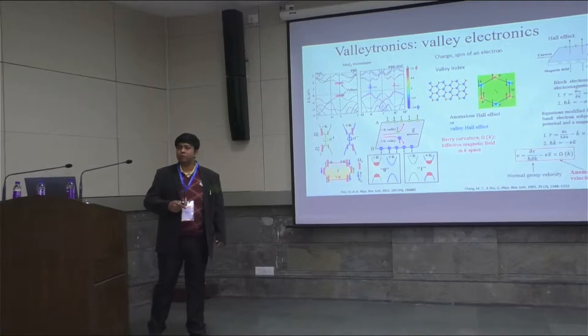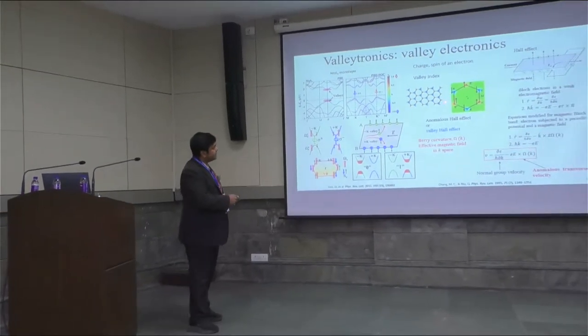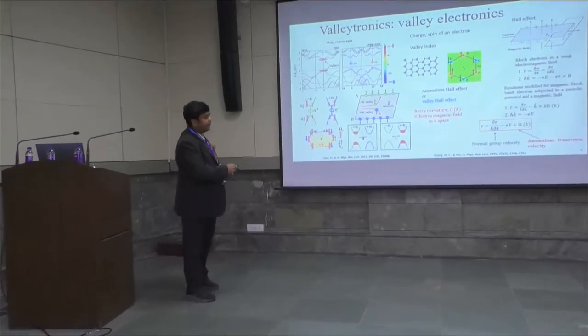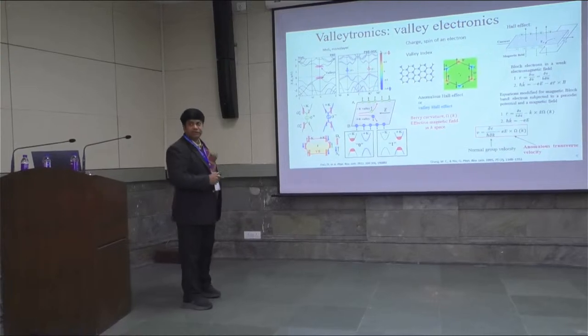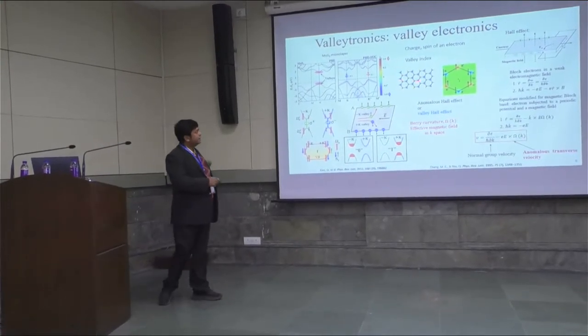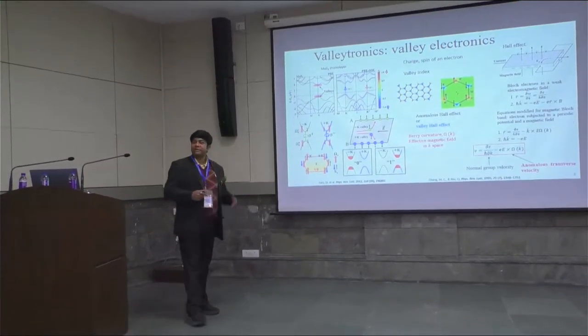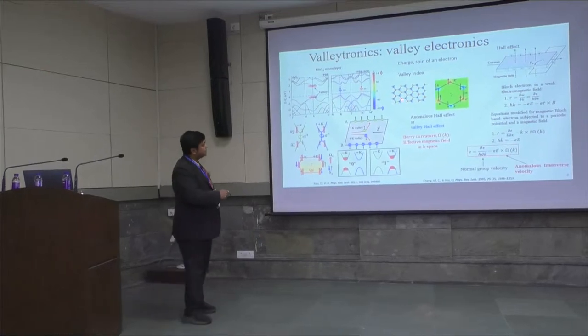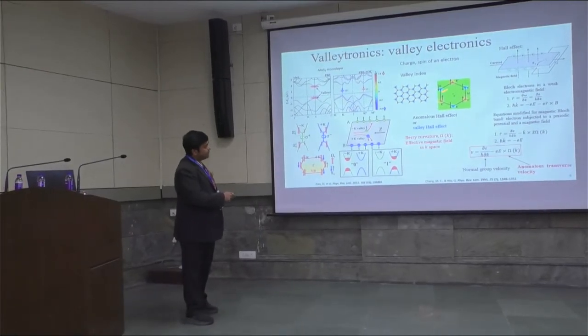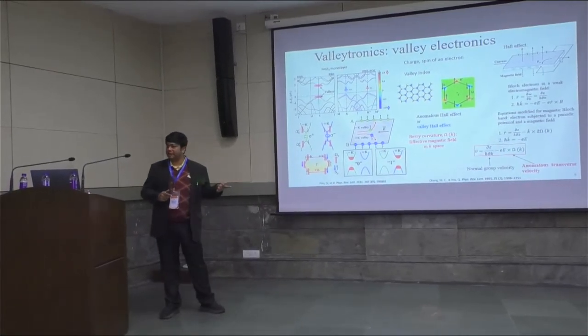The inversion symmetry is broken. Therefore, the opposite spins are locked to this momentum value. This K and K prime becomes distinguishable in MoS2. In a single layer pristine graphene lattice, all the atoms are that of carbon, and therefore K and K prime are not distinguishable in graphene.